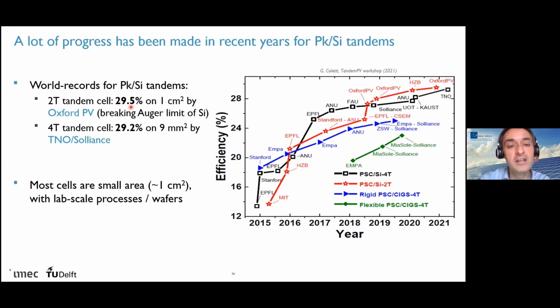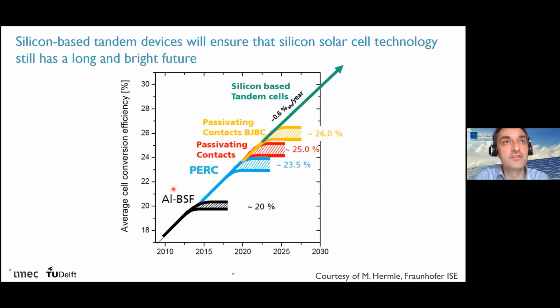This will really be our way forward to reach efficiencies for silicon PV modules produced by industry above 30%. For now, all these results are still on small area, so there is still a lot of work to be done in the next 5 to 10 years to upscale this and make it a reliable technology with efficiencies above 30%. In general, I think the whole crystalline silicon PV community agrees that this is really the way forward, and by switching to tandem cells in 5 to 10 years from now, we will be able to further increase beyond the limits of silicon technology.